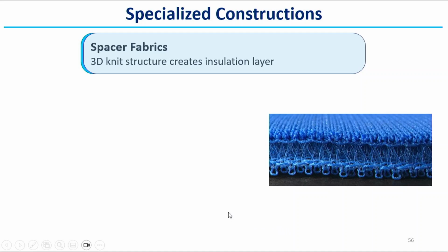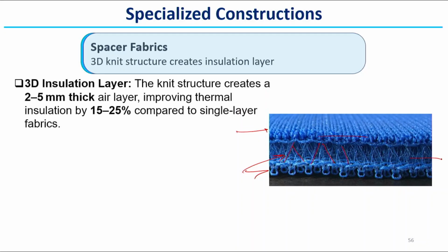And specialized constructions like spacer fabrics are used: 3D spacer fabric, where between two layers of knitted fabric the spacer yarns are incorporated, typically in vertical orientation, which allows a large volume of air to be entrapped within this structure between the two layers. So, the 3D insulation layer is there; the knit structure creates a 2 to 5 millimeter air layer, improving the insulation typically by 15 to 25% compared to single layer fabric. For the same weight, it will have more insulation due to this air layer entrapment.